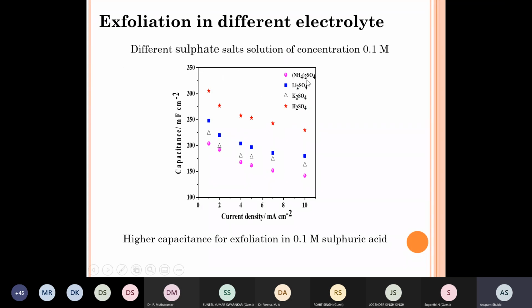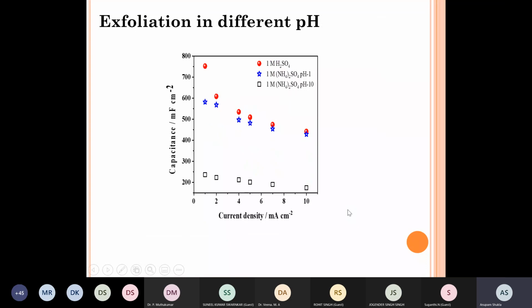And then we looked at the effect of the counter ions. So we looked at different sulfate salts as electrolyte for exfoliation, all solutions having a concentration of 0.1 molar. And we saw that the best results were obtained in sulfuric acid solution. Now, one of the things with sulfuric acid is that the pH is different from other salts. So we managed the pH of these salts also, and in order to do that, we conducted studies at different pH. And what we found was that the pH of 1 molar sulfuric acid, which is 0, gave better results. Of course, 0.1 molar sulfuric acid also gave nearly the same results.